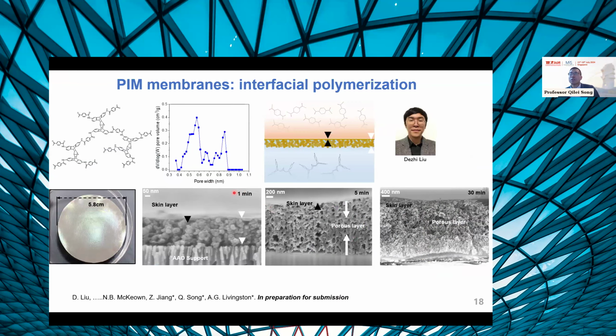Recently, because we still carry on the work on interfacial polymerization, we took some new monomers and combined this chemistry again with interfacial polymerization. So we were able to further improve the porosity of the membranes. You can see that similarly, we were able to tune the morphology of the membranes. We are able to get this kind of heterogeneous structure with a skin layer and a porous sublayer.